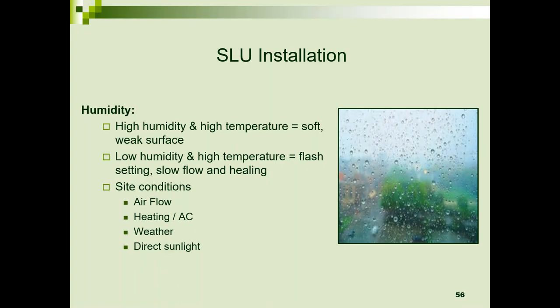Humidity is also a culprit. Too much humidity at a high temperature, you'll get a weakened underlayment. Low humidity at high temperature, you could get a flash, quick set of the material, slow flow and healing. Is the air conditioning or heating running today? Is it running tomorrow? Changes in environmental conditions based on heating and AC can affect the installation of the material.